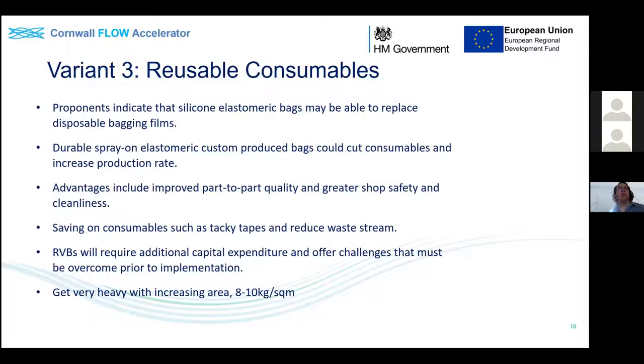So in this one, we're looking at using silicone elastomeric bagging film, where the molding can be done right against the bagging film itself. And we found that you'd produce the blade using this foil, if you like, this elastomeric bag. It'll be removed between moldings, and that would basically be a continued process.